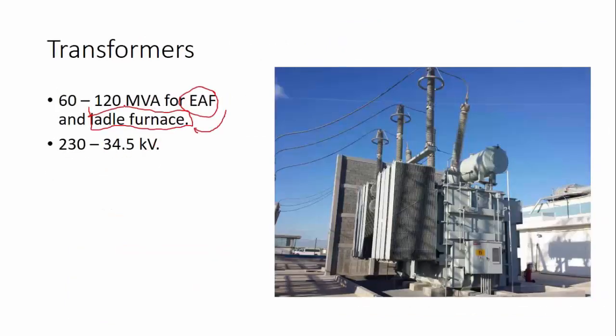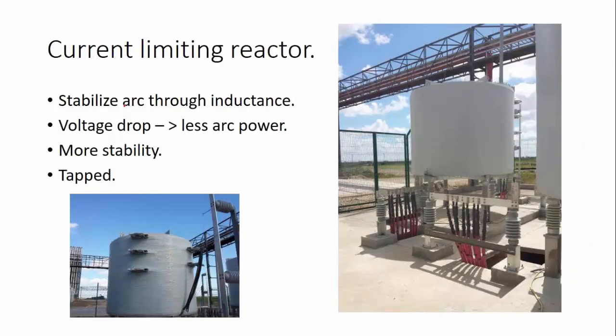So after the main transformer, we will find, in some facilities, and this is quite optional, some facilities have it, some don't, a current limiting reactor, which is a huge reactor that is connected in series between the main transformer and the electric arc furnace. The purpose for this current limiting reactor is to stabilize the arc. It's an inductance, so it doesn't let the current change as abruptly. This reactor will have a voltage drop since it's a series element. Therefore, you'll have less available voltage at the furnace, therefore less power, but a much more stable arc, which is desirable.